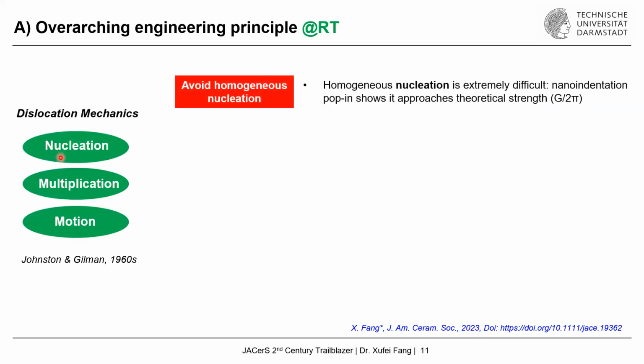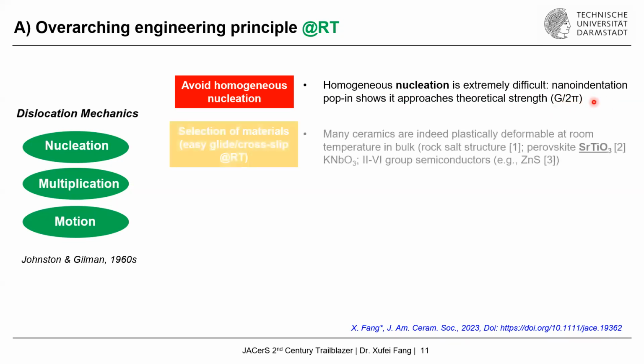Okay, so if we look at the three key factors, dislocation nucleation, multiplication, and motion, our studies in the last years have shown that we need to avoid the so-called homogeneous dislocation nucleation, meaning generating dislocations from the perfect crystal lattice, which is extremely difficult because it requires extremely high shear stress, even approaching the theoretical shear strength, which is the shear modulus roughly divided by 2 pi or 10. And this would be around 10 to 20 gigapascal.